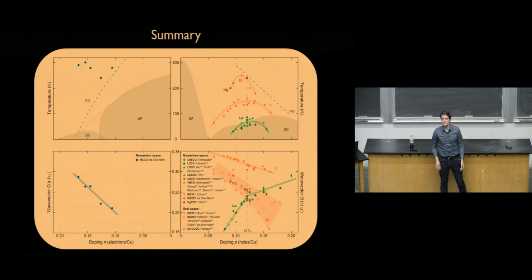You mentioned the antagonism between charge ordering and superconductivity. Is there a possibility of a supersolid type phase where you have coexistence of the two orders? Yes, so they definitely coexist, because even in the superconducting phase, charge order is not completely suppressed, it's partially suppressed. So this is the concept of superstripes that some people have proposed. There's an Italian person that has come up with this, with some theories and some experimental proposals for this type of, I guess you can call it a supersolid type of phase. But that's exactly why we're developing these nano tools.